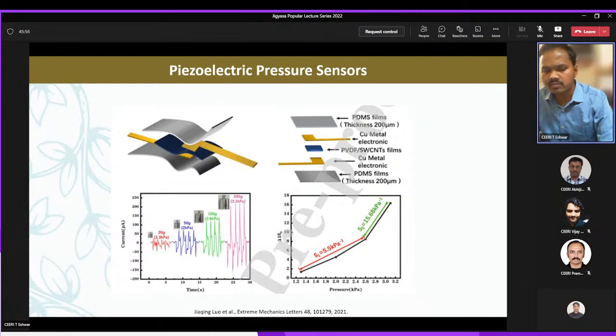Now this can give a spike kind of change in current. This is in picoampere, for different weights like 20 gram, 50 gram, 100 gram and 200 gram. We can see the increase in the amplitude. If we start increasing the applied pressure or tapping, the response increases. But one thing should be remembered: piezoelectric pressure sensors are more suitable for dynamic sensing. If you look here, these are current spikes. We can see the response in the form of spikes, meaning that these are more suitable for dynamic pressure. For static pressure, resistive and capacitive sensors are more suitable.